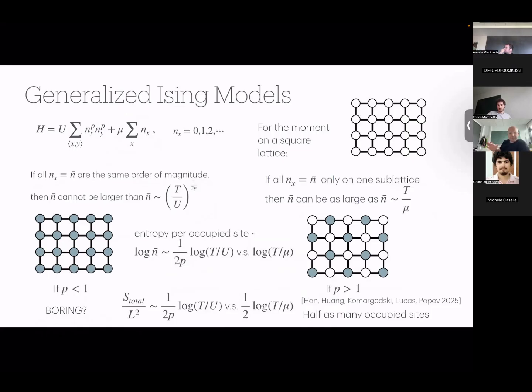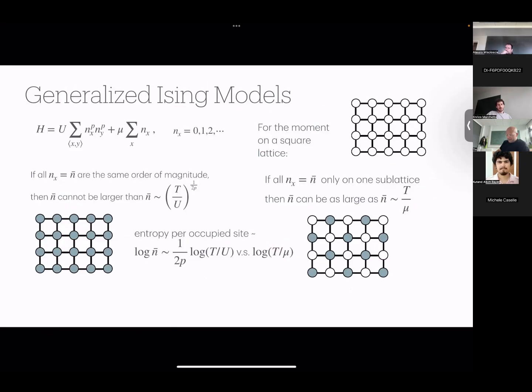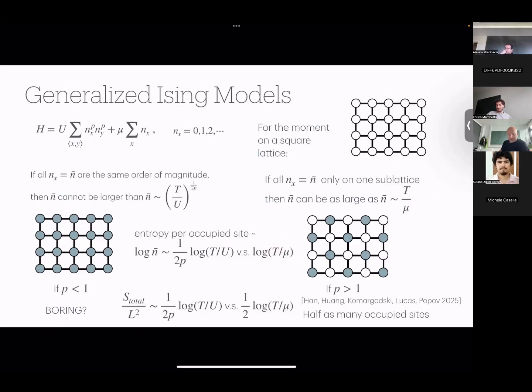But it turns out that in these models, if you do it carefully and compute corrections to mean field theory, they are large. They grow with temperature, and therefore mean field theory is not really justified. However, these gentlemen here did lattice simulations as well, and found that there is order for p equal to 2. They haven't explored other cases, but it seems to be very robust. So what we did in the subsequent paper is ask the question, what happens when p is equal to 1?